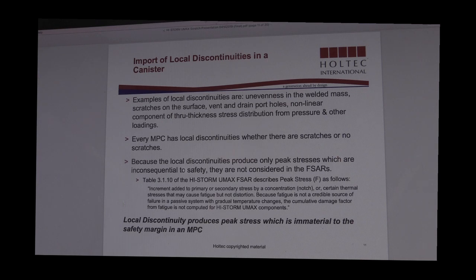I also mentioned brittle fracture. That also is ruled out because the MPC in our case is manufactured from austenitic stainless steel, which is a ductile material, and therefore it is immune to brittle fracture failure, which is also stated in the UMAX FSAR with respect to the MPC. So having ruled out fatigue and brittle fracture, peak stresses are no longer of any concern with respect to the MPC and its structural design. That's why we say here on the slide, in conclusion, local discontinuities produce peak stress, which is immaterial to the safety margin in an MPC.